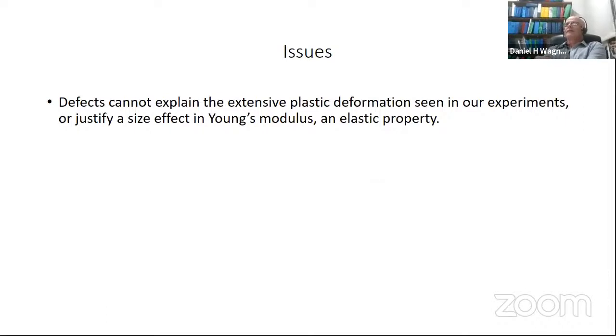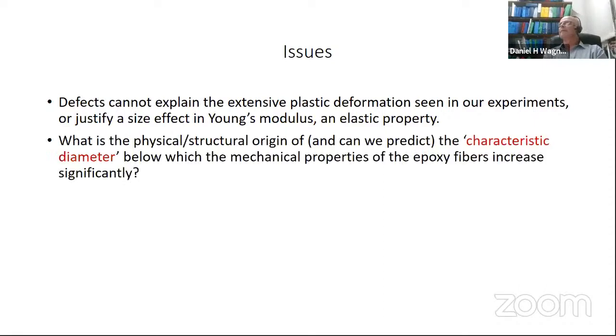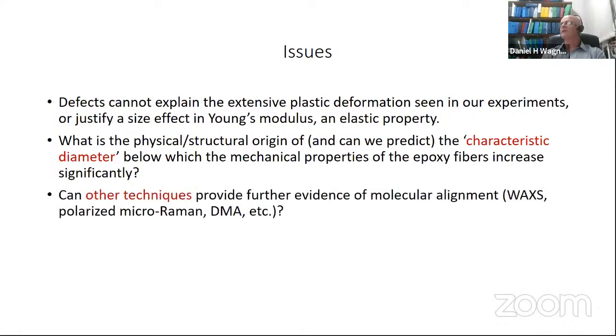So defects, in fact, cannot explain the extensive plastic deformation that we see in the experiments, or justify size effect in Young's modulus, which is an elastic property. A question we have is, what's the physical structural origin of the characteristic diameter? Is there any way we can predict what is the value of that characteristic diameter? So what's the physics, again, below which the mechanical properties of epoxy fibers start increasing very significantly.